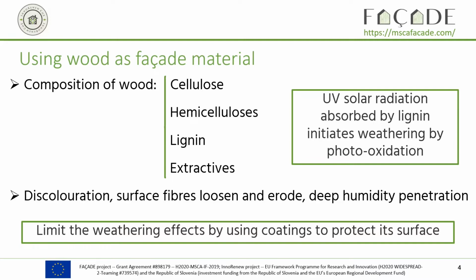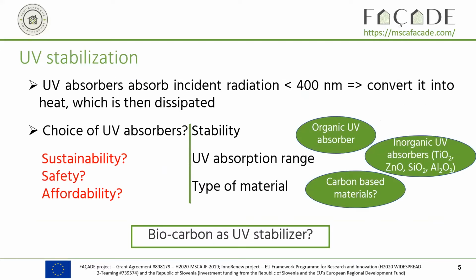It will absorb it, and this will initiate the weathering by photooxidation. So it will conduct to discoloration and then to loosening of the fibers at the surface, erosion, and with this erosion, it will make possible to have penetration of humidity in the wooden surface. So for all this reason, we try to limit this weathering effect, and for this we will use coating to protect the surface of wood.